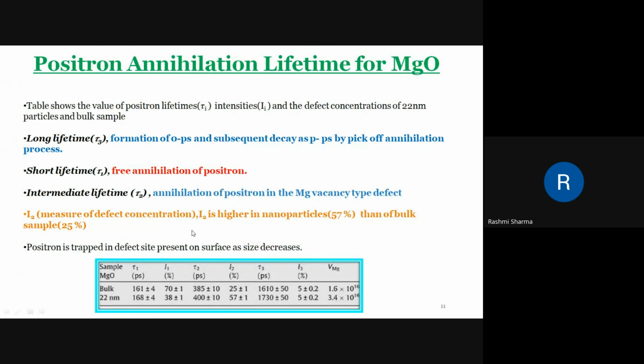I2 is the measure of the defect concentration. Here we can see that the defect concentration in bulk material is smaller as compared to the nanomaterial. So from this result, it is clearly visible that the defect concentration decreases with increasing particle size.